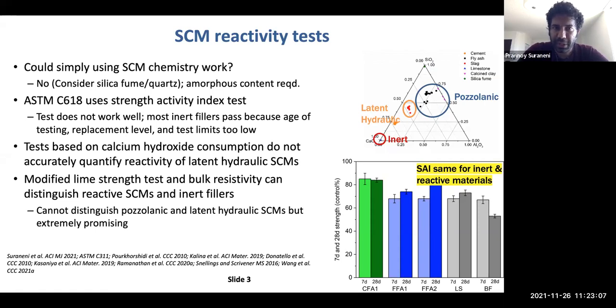There are a lot of tests historically which are based on calcium hydroxide consumption. These can be really useful for pozzolanic materials, but they are not accurate indicators of reactivity for latent hydraulic SCMs such as slag. Lime strength and modified lime strength are very interesting. Mike Thomas's group has done a lot of work on this, and bulk resistivity, where we've done a lot of work. These are two incredibly interesting test methods. They can distinguish very well between reactive SCMs and inert fillers, but they cannot exactly distinguish between pozzolanic and latent hydraulic SCMs. But at the same time, they are incredibly useful techniques. I'll talk just a little bit about bulk resistivity in the next couple of slides.